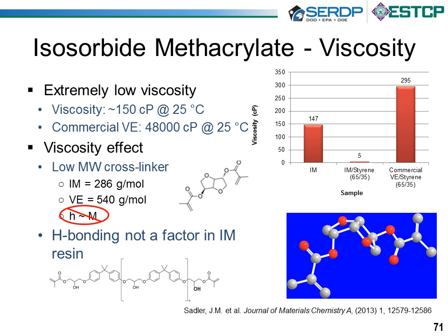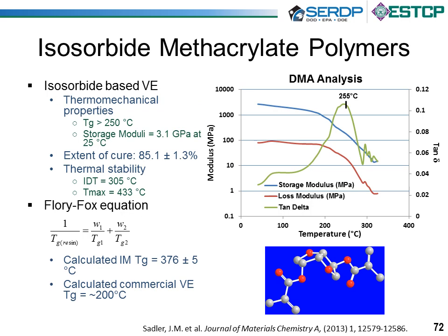The molecular weight is only a slight difference, about half, and we would expect the viscosity to be proportional to the molecular weight unless there's another factor, which indeed there was. We found that hydrogen bonding, or the lack thereof, in isosorbide methacrylate was the reason for this much reduced viscosity. So this isosorbide methacrylate is beneficial in that you can replace styrene entirely and the vinyl ester itself and make a nearly 100% bio-based vinyl ester resin using this isosorbide methacrylate that's very easy to process. Now, how are the properties? If we look at the next slide, we could see properties like, in particular, glass transition temperature and modulus were excellent.